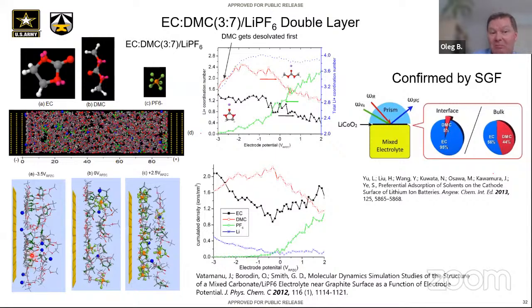Why? Because that's how they rearrange their dipole in order to screen the majority of the surface interaction here. DMC cannot do that effectively. And because of that, EC will have a preferential interaction, as I'll show. Now coming back to the positive electrode, we see both solvents and anions. The point is that at reasonable concentrations like 1 molar, there are just not enough anions to completely get to the surface of the cathode and expel all solvent. So all species are going to be present.